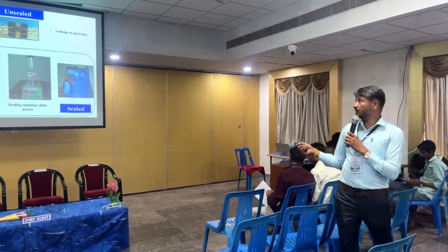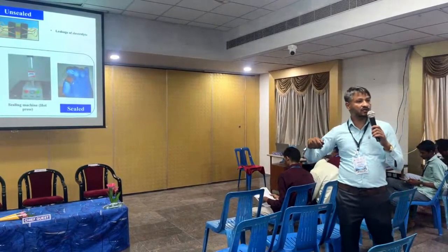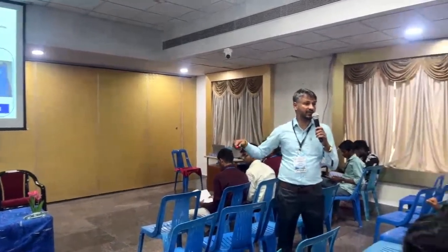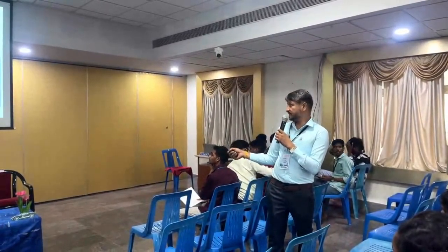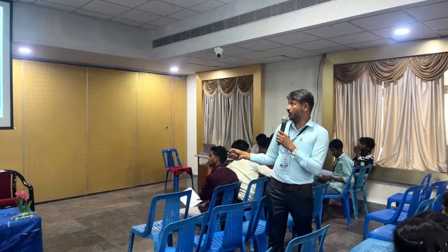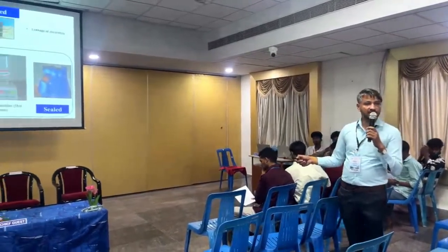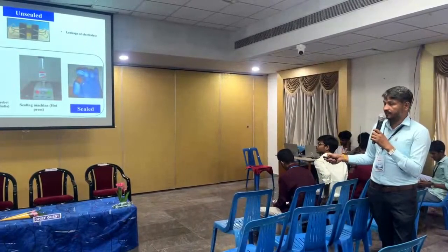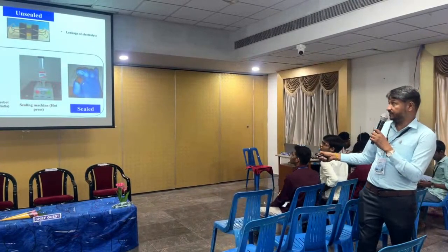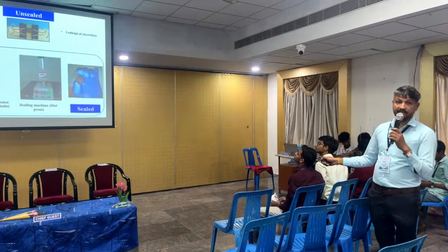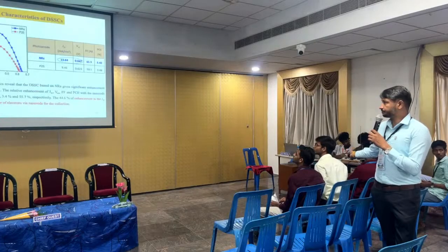So conventionally we used electrolyte, and through the gap we usually inject the electrolyte. There are always leakage issues. So in order to avoid that, we made one small hole in the FTO substrate. Through the hole we inject the electrolyte. In this way we can arrest the leakage. So you see, there is a sealed device. Then, with the help of a polymer film, we seal the device. So we can improve the stability by the sealing process. You see again the improvement in current density here also.